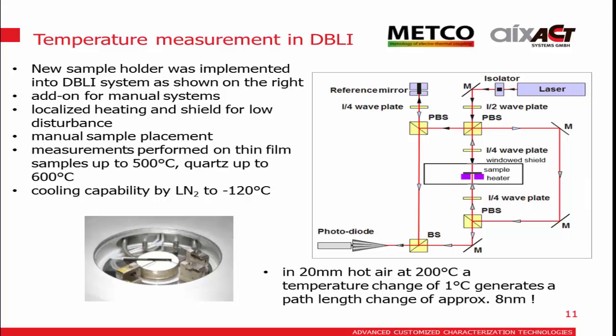Just a rough calculation: in 2 centimeters of hot air, a 1 degree change already generates 8 nanometers of deflection, which you would visibly see. So that means you would have to maintain a stable temperature.